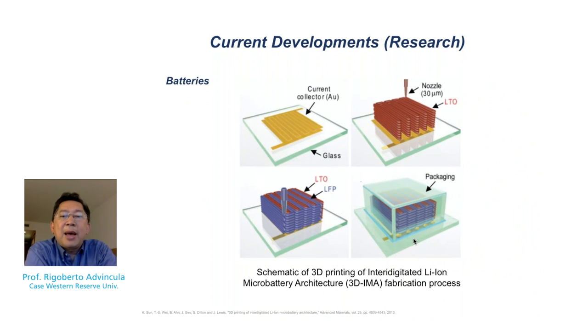In the development of batteries, there could be interest in making interdigitated electrodes, let's say in a lithium ion micro battery architecture. One can first deposit the current collector, which could be gold or other highly conducting metal, and then one can deposit the LTO, followed by the membrane, LFP. One can, without going into a further deep dive on lithium ion batteries or lithium sulfur batteries, then needs to have this enclosed in a packaging unit, and then finally access through the anode or the cathode, where the lithium ion exchange or mobility facilitates its action in energy storage.